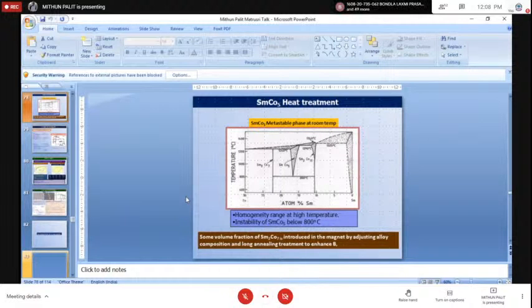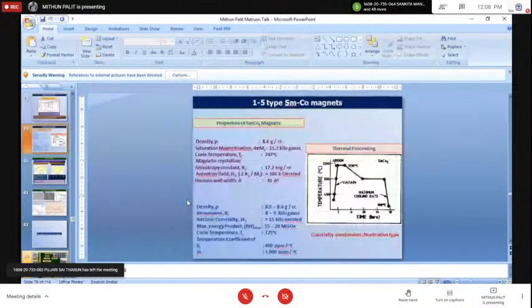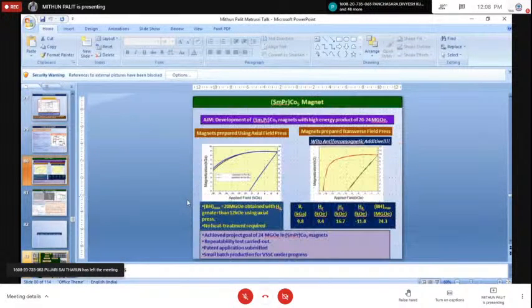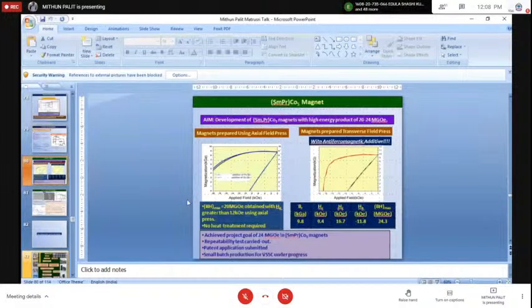The other nucleation type of magnet is the SmCo5 magnet. The process is similar to 2-17, so I will not go into detail about it. This magnet is also processed through the powder metallurgy technique. Of course, we don't get the energy product as high as the 2-17. However, we get a reasonably good energy product of 15 to 18 megagauss-oersted in the SmCo5 magnet.